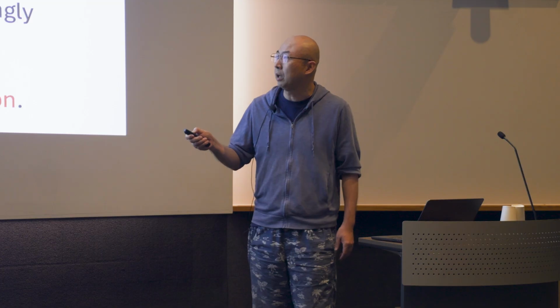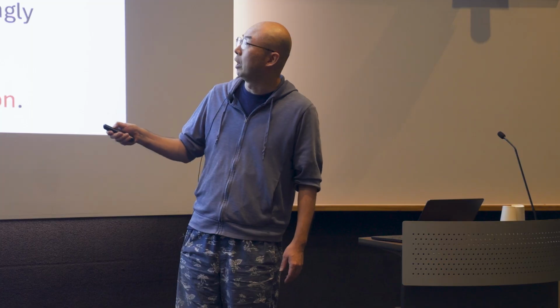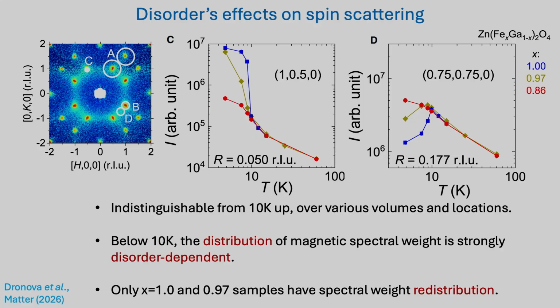So you don't have any actual accumulation or slowdown for the disorder sample. However, the distribution in the reciprocal space does change. So if you see here, up to 10 Kelvin, if you change the integration volume to have a very small volume at the Bragg peak, or a medium volume around this interstitial region, up to 10 Kelvin, the accumulation is still the same. So that confirms our previous picture that we cannot tell the difference between the spin fluctuations across three samples up to 10 Kelvin.